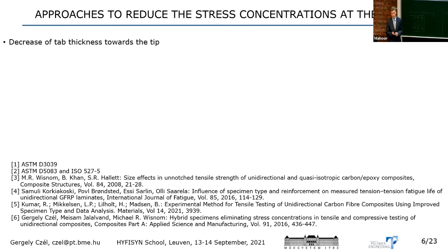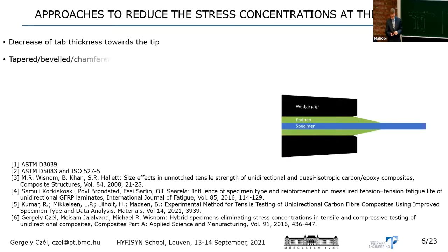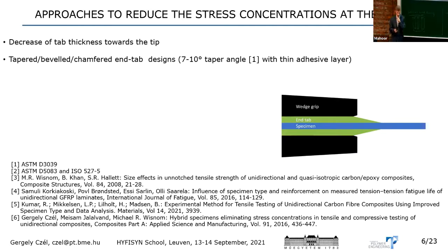And one way is to design the end tabs so that they lose stiffness towards their tips. So they get less stiff towards their tip. And this is the standard design, or one of the standard designs, of the end tabs, so that we have a taper, a shallow angle taper. The recommended angles are below 10 degrees, and this way we have a section of the specimen where we have less and less added stiffness coming from the end tabs, and finally it fades away. So in a way it distributes the stress concentrations. It sounds funny. The word concentration is right the opposite of distributing. But anyway, we try to smear out a little bit these stress concentrations.